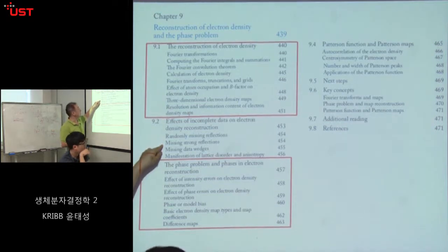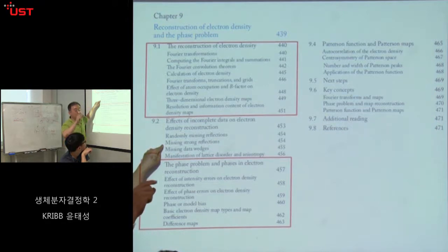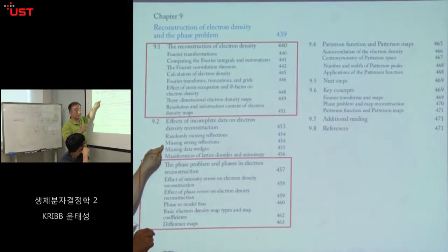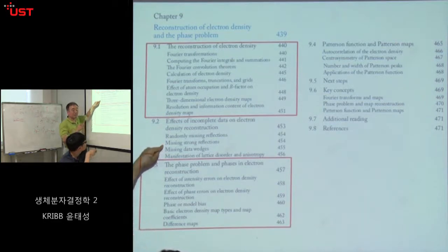Secondly, strong intensity data missed due to some reason. Some reason is like this: overflowing intensity for very strongly diffracting crystals. Then we have a problem of not having the correct structure in low resolution structure, kind of rippling effect. But in terms of higher resolution, it's less detrimental.